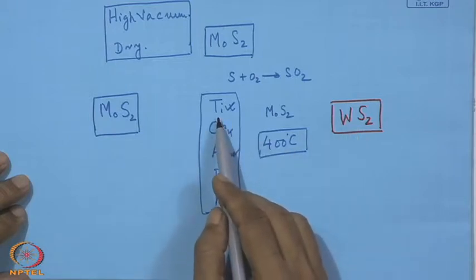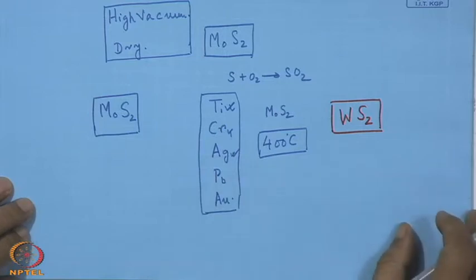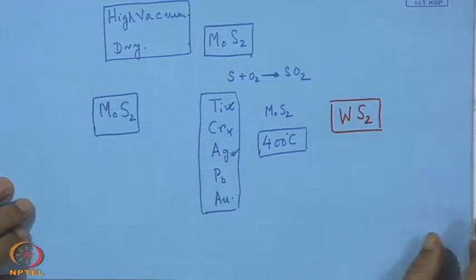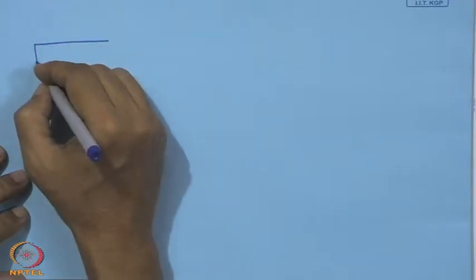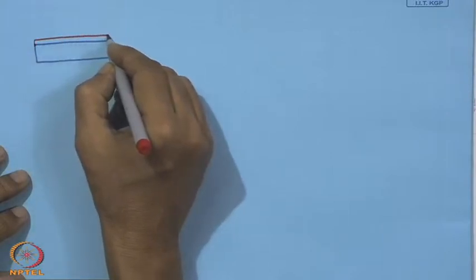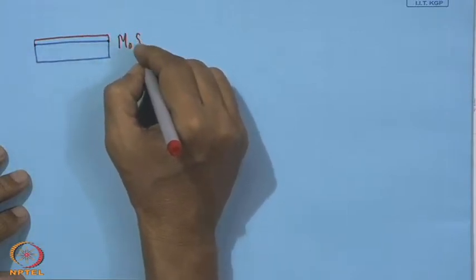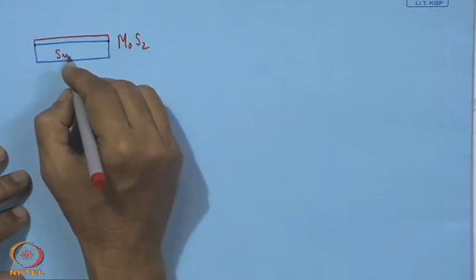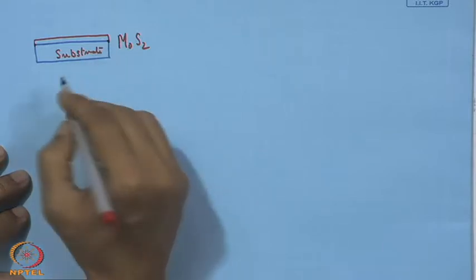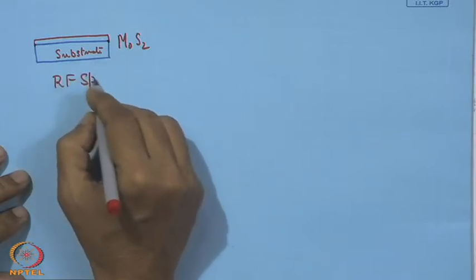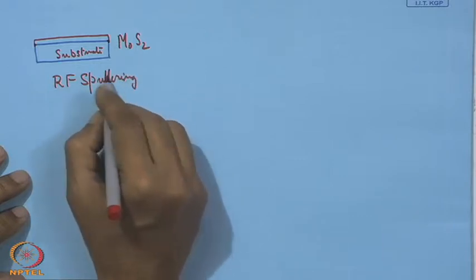Whatever may be the case, the routine practice for these coatings is not just MoS2, but to have doping of titanium with MoS2. So, the basic architecture of the coating, which was used with RF, was just MoS2, and it is mostly a columnar structure. So, this is the substrate, and on that we have the MoS2 coating, and it is mostly RF sputtering with just conventional magnetron RF sputtering.